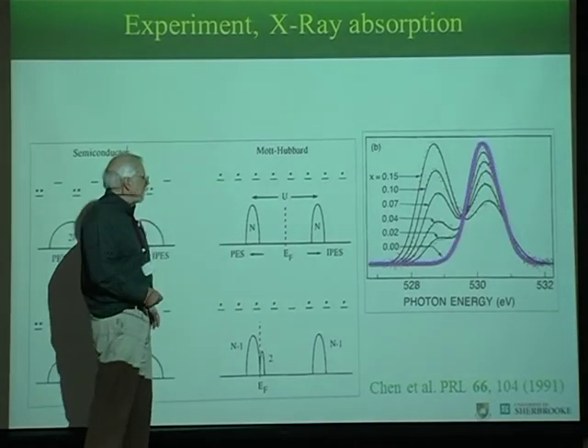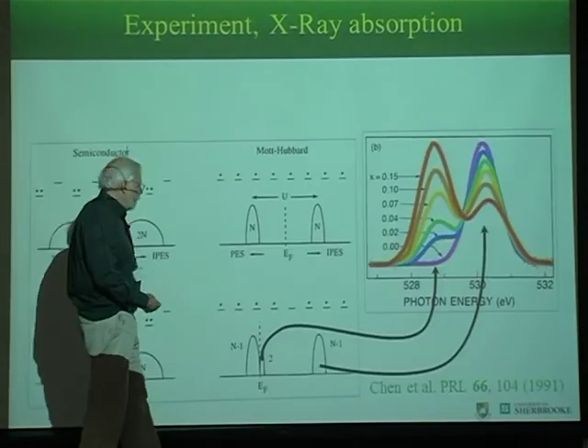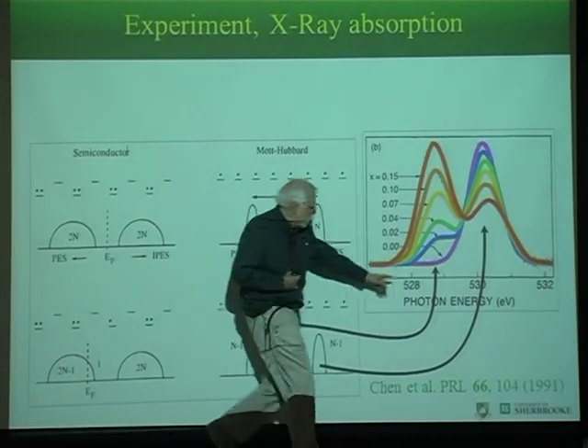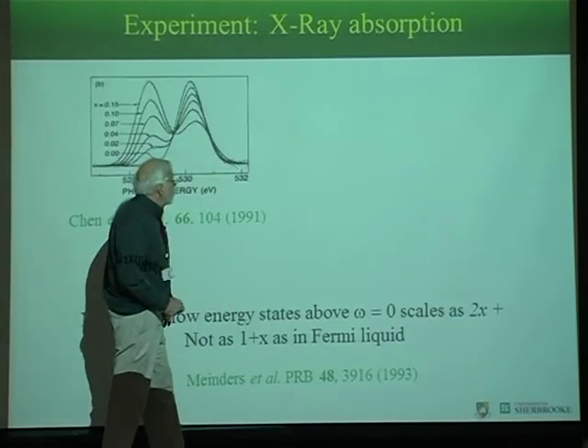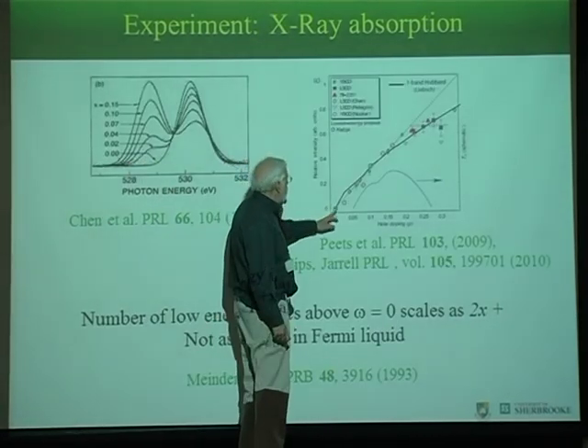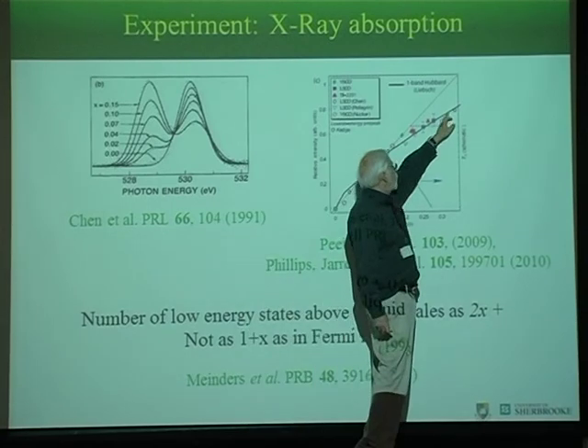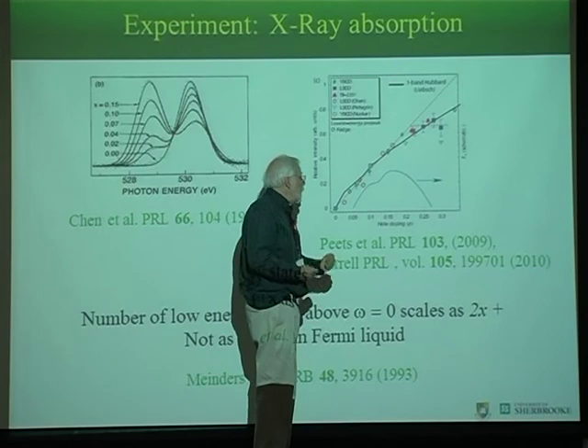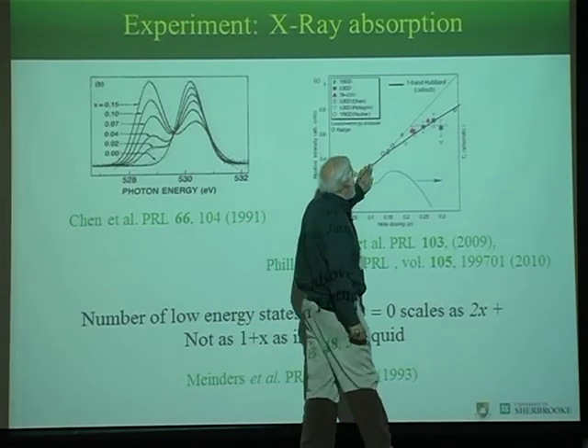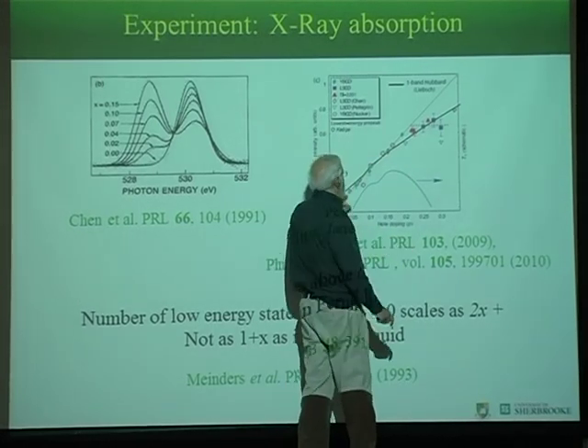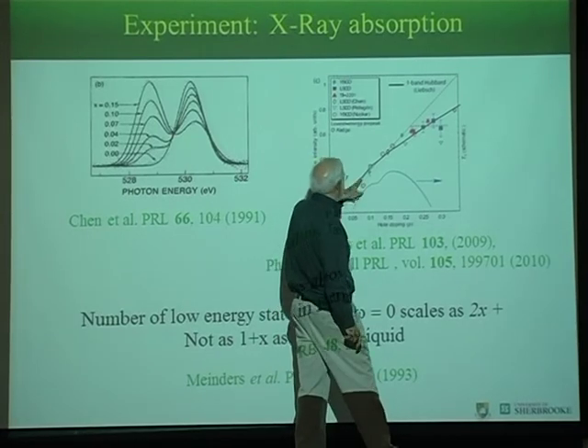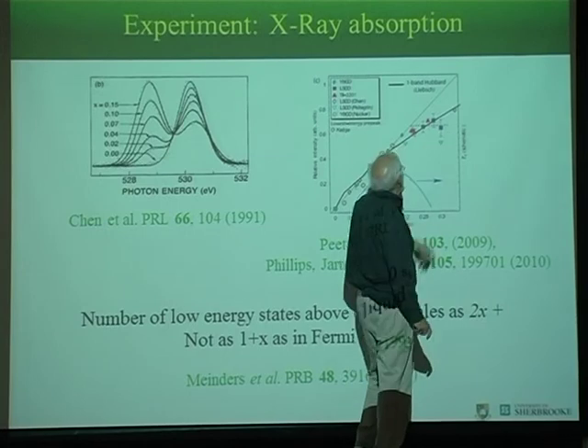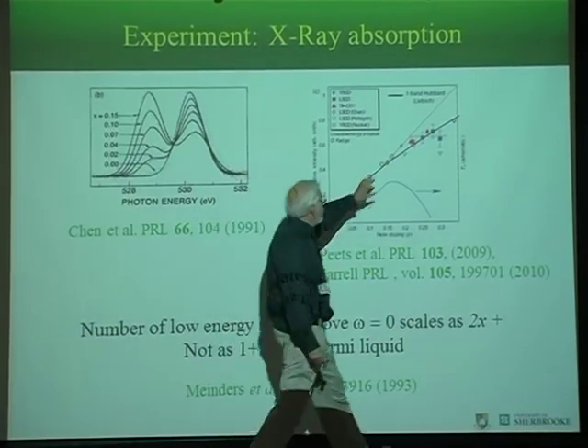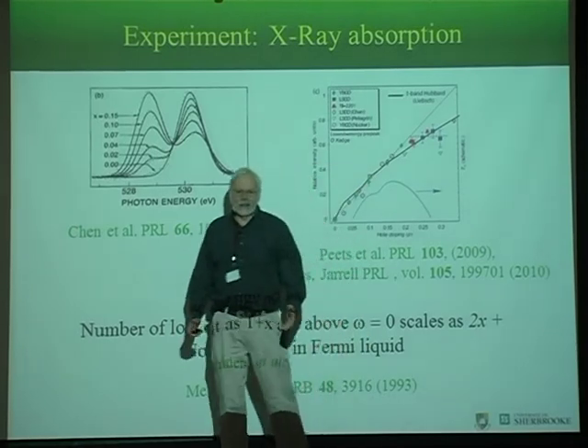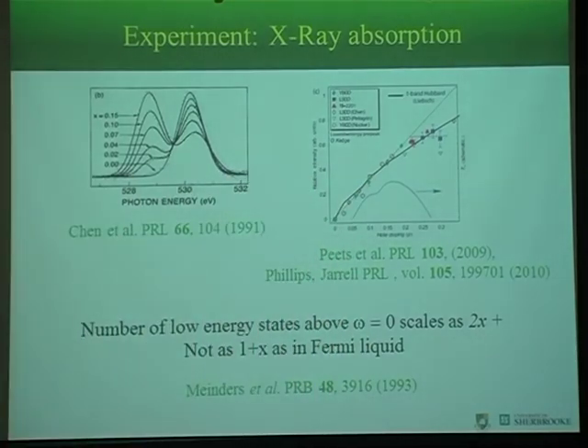And as I say, if you do some Hubbard model, these arrows show where the weights are coming from. It's coming from there, it's coming from there. And if you look at cluster dynamical mean field theory, this solid line is what you would expect for the weight of this lower peak, and the experiments are all these scattered points here. Now this group that published this PRL first said this is inconsistent with the Hubbard model. Here it is, and here it should be flat. But in fact, if you look at the error bars, the black line fits just as well in the single band Hubbard model. Does that answer your question?